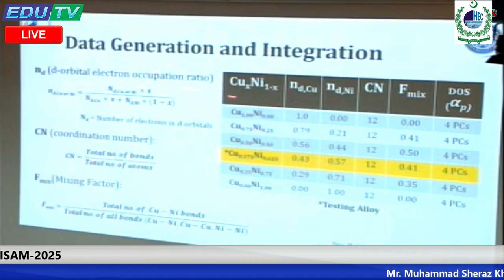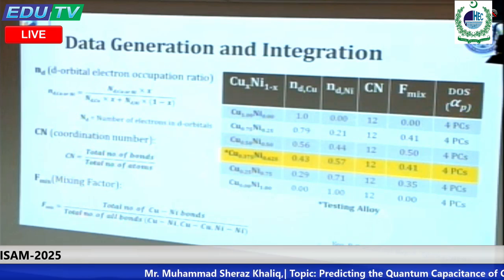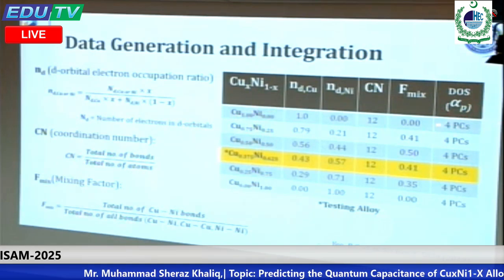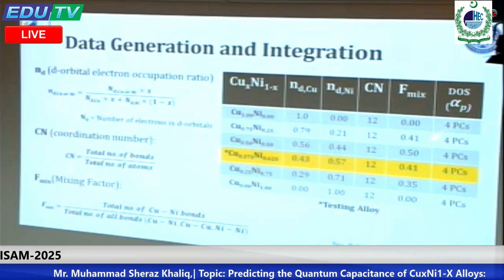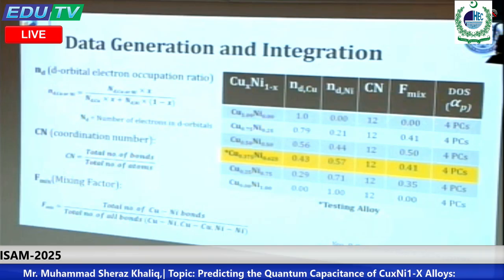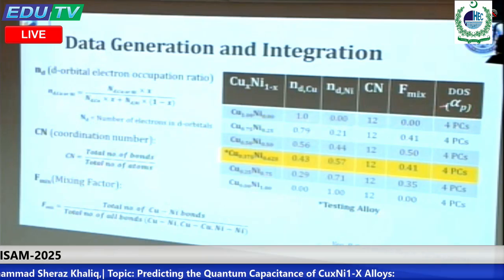d orbital electron occupation ratio, and then there is a coordination number of each composition, and then there is a mixing factor, and we calculate these ratios for the desired composition, and also the principal components that we can calculate from the DOS. And for each composition we will consider 4 PCs. Those 4 PCs define the whole variance of each DOS and reduce the unwanted noise, so we can concentrate over the whole process.